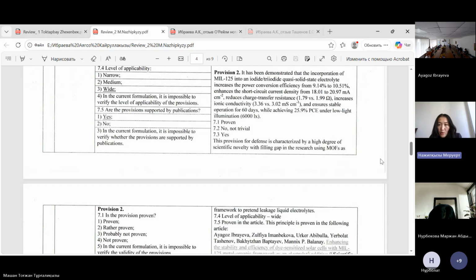20.97 milliamps per square centimeter, reduces charge transfer resistance from 1.79 to 1.99 ohms, increases ionic conductivity, millisiemens per centimeter, 3.36 to 3.02, and ensures stable operation for 60 days while achieving 25.9% PCE under low light illumination, 6000 lux. According to provision 2,